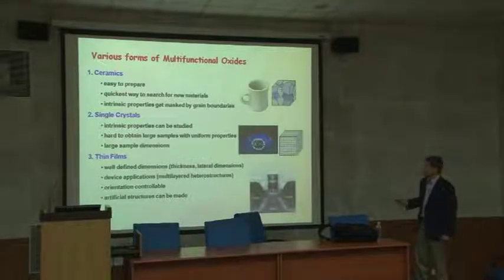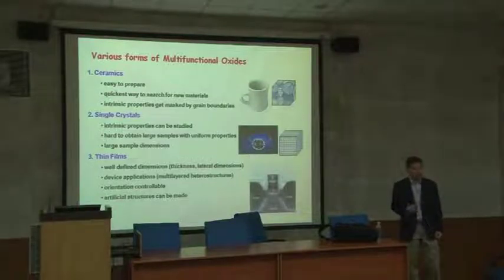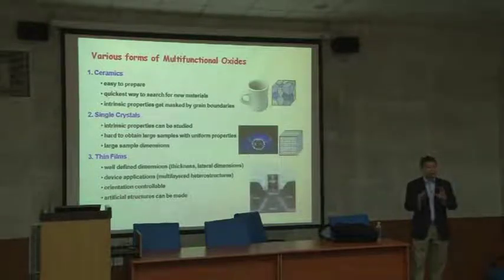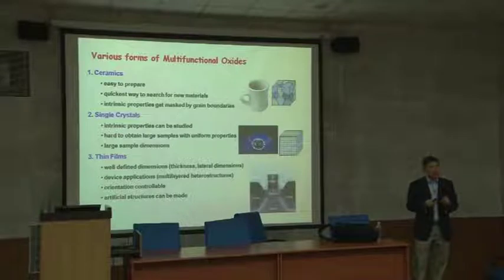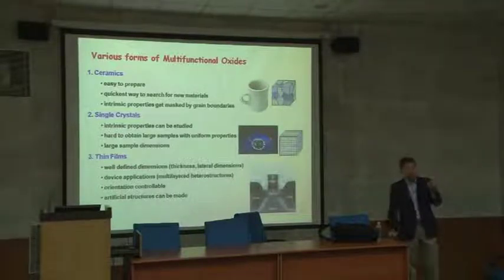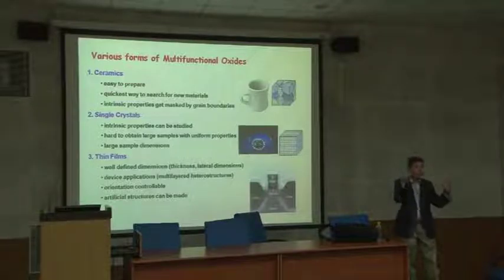And the reason why large crystals and uniform properties are very hard, there are many reasons for that. When you grow a single crystal, there are many different single crystal growth techniques. Sometimes people use Czochralski, sometimes the Bridgman method, sometimes gas transfer method, and a lot of flux growth methods. There are many different methods people use. But when you grow large crystals, the oxygen diffusion through the large distance is very, very slow. You know, solid-state diffusion is very, very slow. The surface region has good oxygen stoichiometry, but inside it is oxygen deficient. So that's one of the problems of making large single crystal materials.